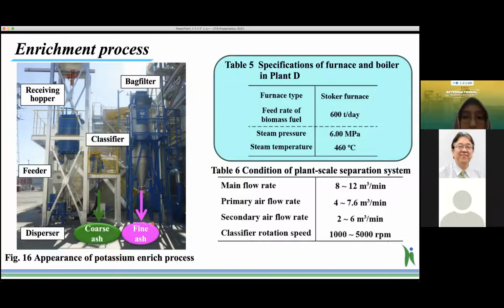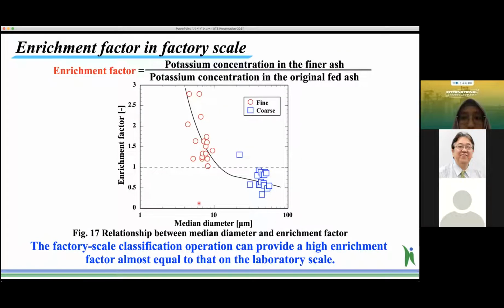The cut size of the classifier was easily varied by changing the experimental conditions listed in table 6. With this factory scale plant, we investigated the possibility of the enrichment. Figure 17 shows the relationship between the median diameter of classified ash and enrichment factor. The enrichment factor rapidly decreases with increasing mass median diameter, then it decreases more gradually.